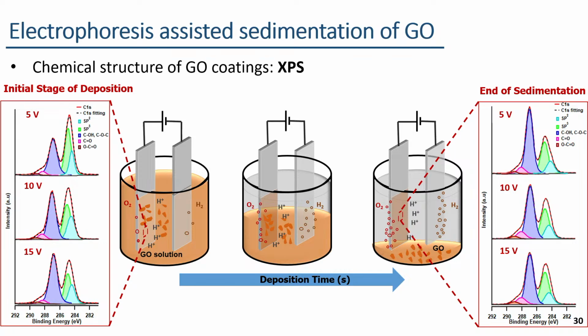Then comes the XPS analysis of these coatings. Here I have shown the XPS carbon 1s spectra of these GO coatings obtained at the initial stage of deposition and at the end of the sedimentation process under different voltages. So, here the GO coatings obtained at the initial stage of deposition under low voltages show